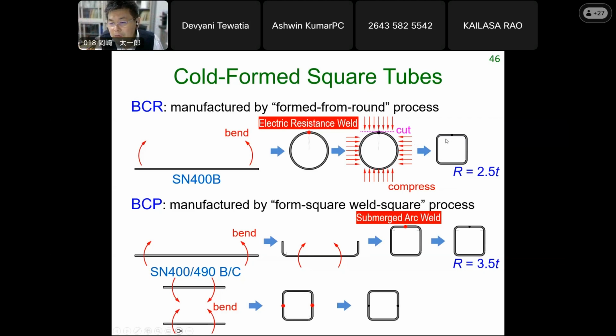Now, what happens with cold forming, especially at this corner? As I write here, the outer radius is 2.5 or 3.5 times the thickness. Now, this is quite substantial bending. What happens is that you strain harden the material, but there's also the aging effect. Aging is that after you plastically deform the steel, there is a further increase in strength and loss in ductility with time. The aging saturates after a couple of months, but there's this dual effect that exaggerates the strain hardening. We recognize this, and we confirm it from testing, and we do impose requirements so that these effects do not grow to be too large.